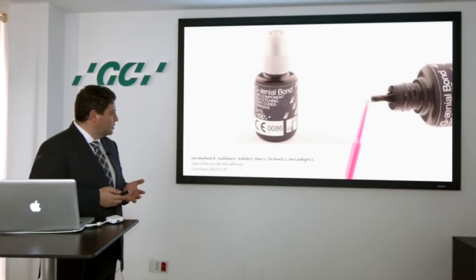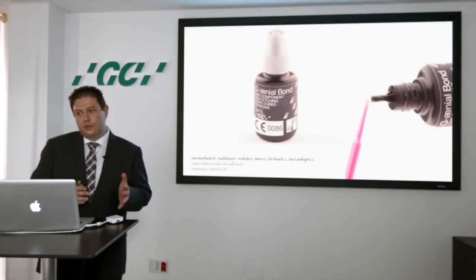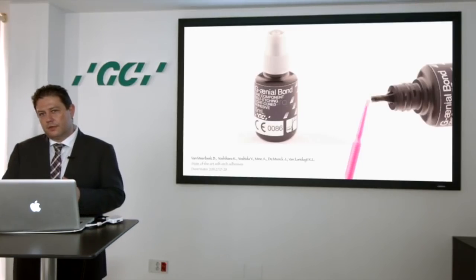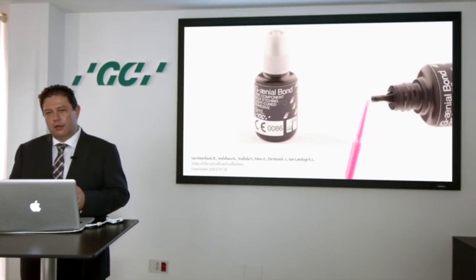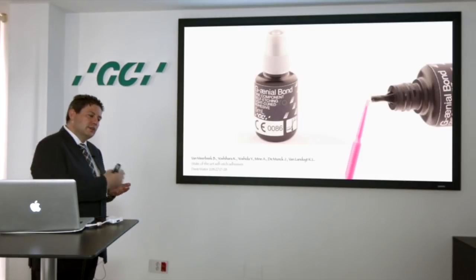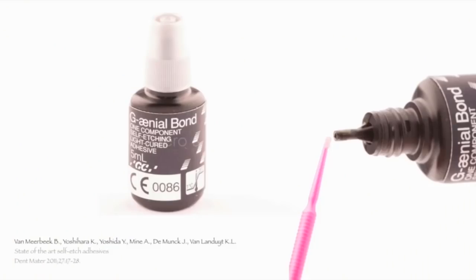But the fact is that if you use any adhesive on the market, use it in a proper way. For example, if you use an auto-etching system in posterior that is very good for the dentin, use the auto-etching, etch the enamel beforehand, and you will have very good results. Apply different coats, eliminate the solvents well, and you will have very good success.